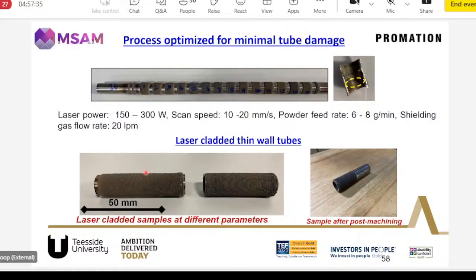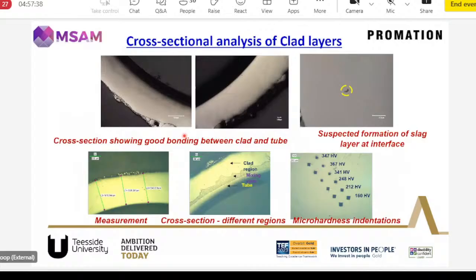So when we go to the cross-section analysis, we could see this continuous variation in the cross-section. There is no defect formation except for some micro pores, which is generally expected in laser cladding or laser additive manufacturing. But we can see that there's a smooth gradation. You can see that the tube is here, the mixing zone is there, and we have the clad region. So there's a smooth change in the composition from the tube to the clad region. And this material that we have deposited here is an oxidation resistant material, and these materials are used a lot in the next generation nuclear reactors.